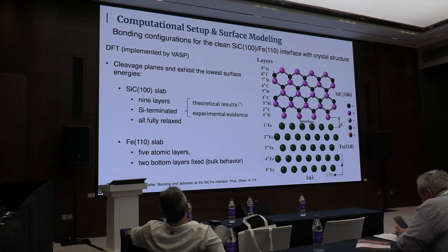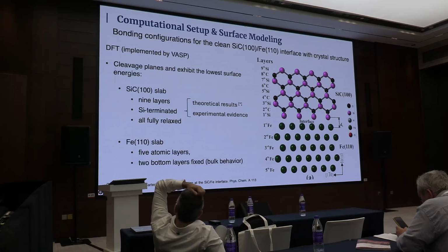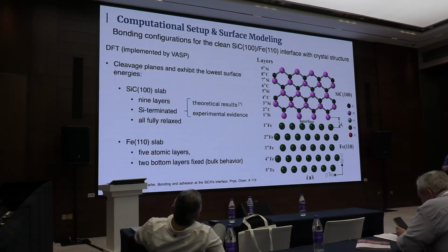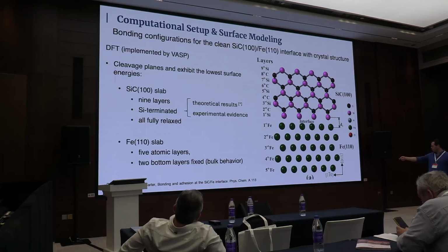So because this will be an interface, we will relax all the atoms in this structure. But because this will have to behave as a bulk, as a substrate, it means that it will be deep in the material, and in the lower part I want to keep the behavior of the bulk situation. Thinking at the atomic level, from the first layer in the pure iron practically nothing happens, different from the surfaces, which will be considered from these 2 layers.